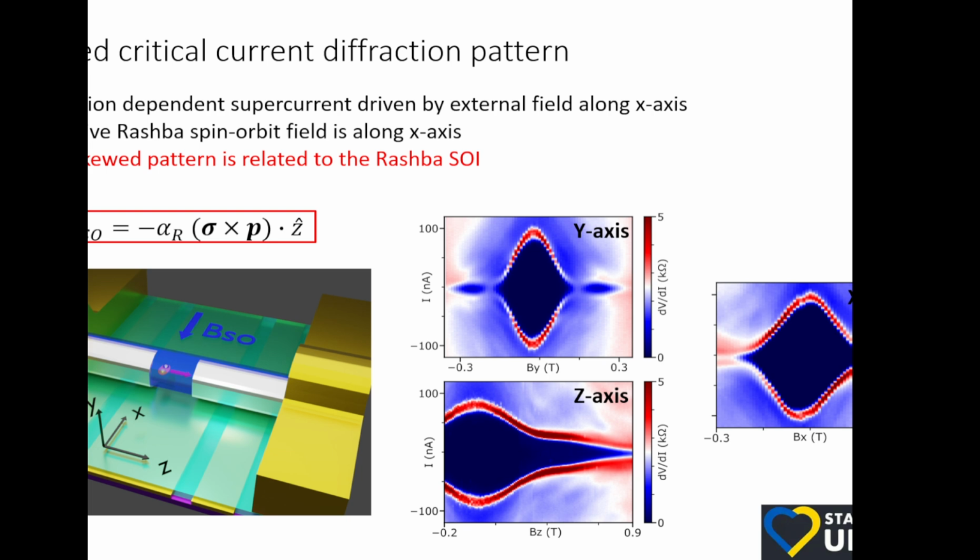And the other reason is this shell of superconductor is very, very thin. It's 15 nanometers thick, and along this direction, the field is perfectly aligned with the shell. No matter where it lies on the wire, along this one axis, we're always looking into the film. And so to kill superconductivity in this thin, you can go to very high field.